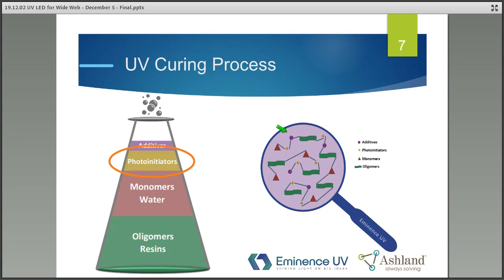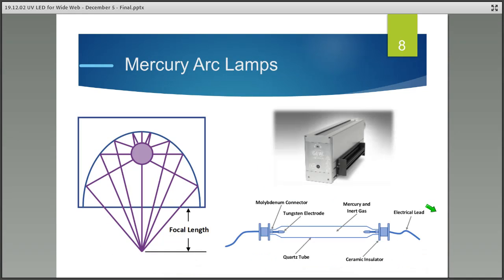So what happens is the formulators take these ingredients and they blend them together. Each one of these images within this magnifying glass represents one of those components. The four-sided star is the photoinitiator, which absorbs the UV light and creates free radicals, which transfer energy. And all these particles then combine to form one long continuous chain. And this process, if you're not familiar with it or you haven't seen it, is instantaneous and happens as soon as the material is exposed to the UV light.